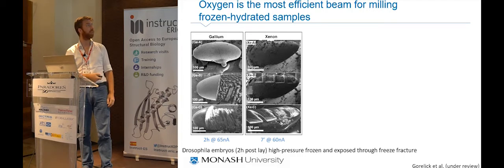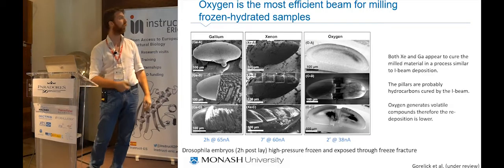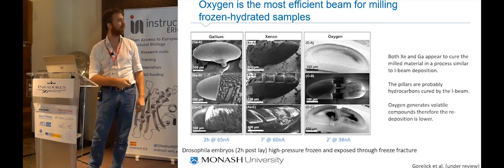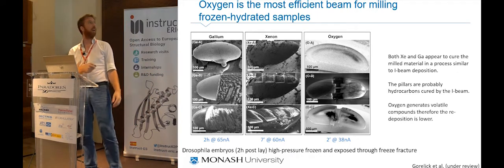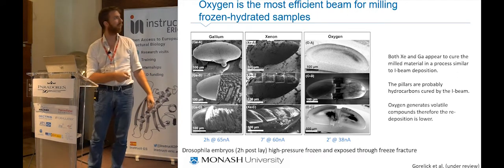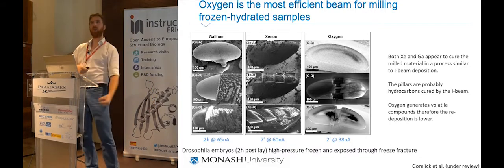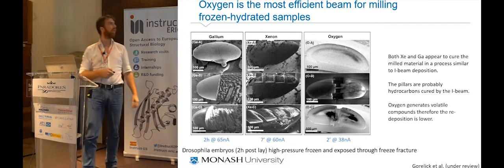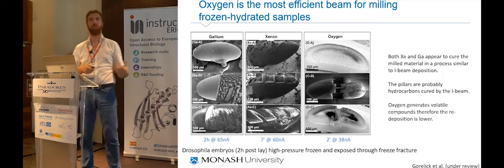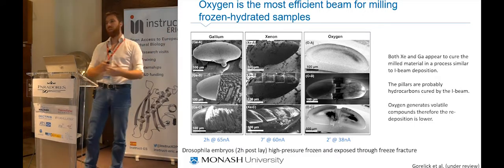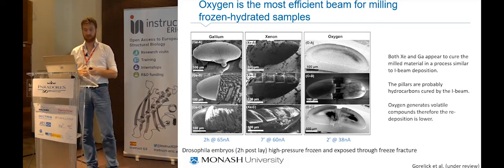So we thought, okay, let's do oxygen. It works so well, and it does work actually. In 2 minutes at 38 nanoamps, because that's the current that I can extract in that range, we actually can cut all this. We can make a lamella throughout a whole embryo. It's not a nice lamella. It's not a lamella you would use for TEM, but I can cut through. So that's actually nice. I thought, okay, that's cool.